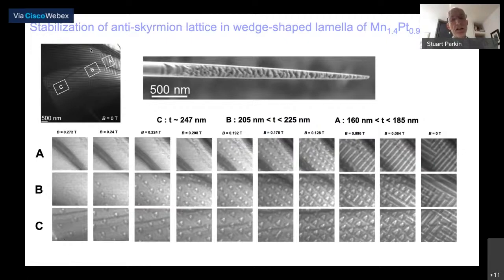When it doesn't form anti-skyrmions, it turns out that the structure forms instead a helical structure, and the helices are oriented along two crystal directions which favor Bloch domain walls in this anti-skyrmion structure. And so in the left, you can see these black and white lines. These correspond to magnetization pointing to the right and to the left in the plane of this material as the magnetization undergoes a helical variation along a given direction with a given period, and the period of this helix is determined by the ratio of the Dzyaloshinskii-Moriya exchange to the Heisenberg exchange that favors parallel orientation of the magnetization.